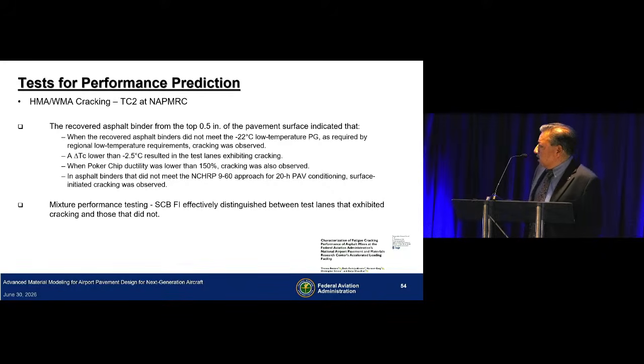What we found is that when recovered asphalt binders do not meet the minus 22 degree low temperature PG grade as required by the regional low-temperature requirements, we observed cracking. Out of 6 sections that we tested, only 2 showed cracking, and these 2 had different warm mix additives. The lab tests showed that a delta Tc lower than minus 2.5 degrees centigrade also resulted in test lanes that showed cracking.